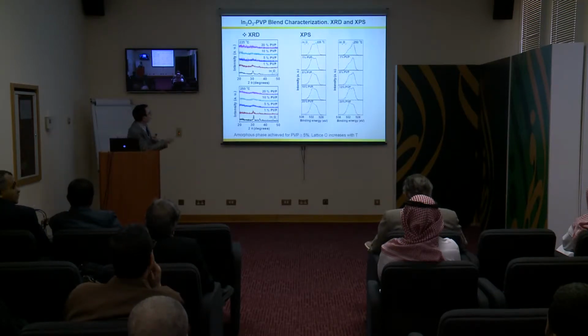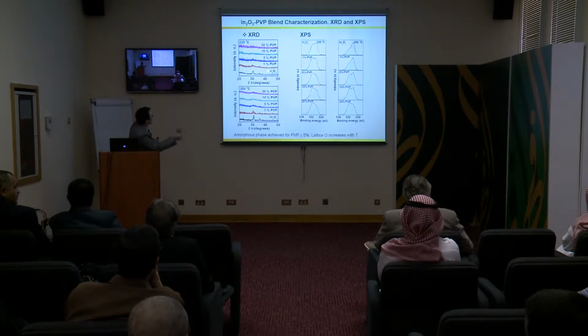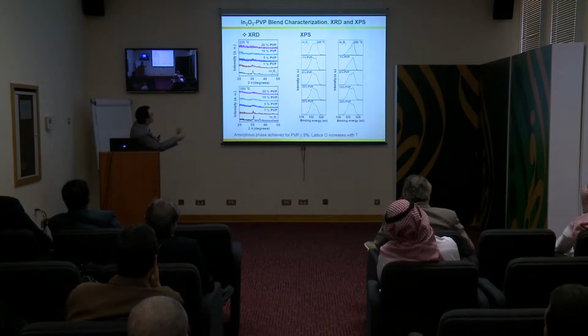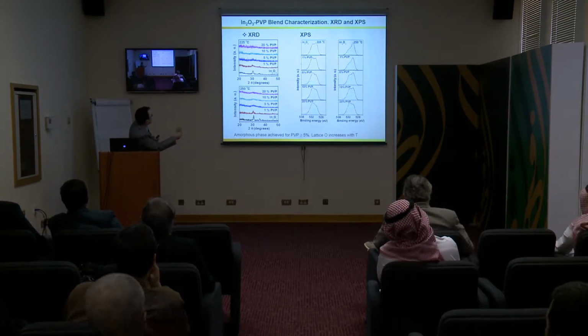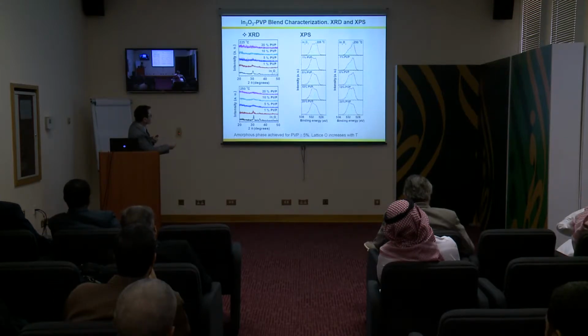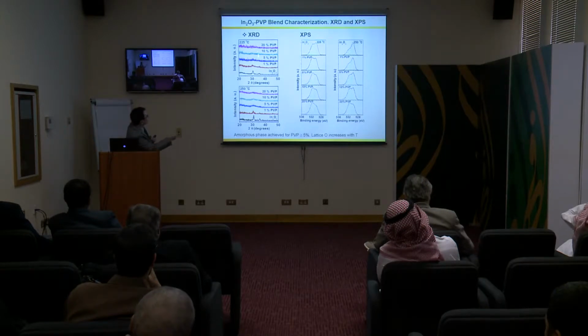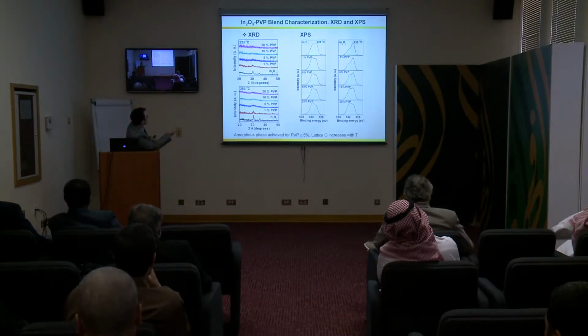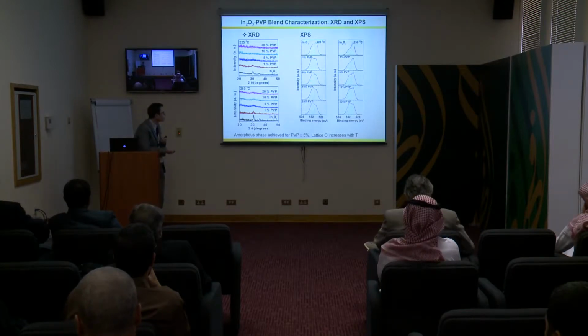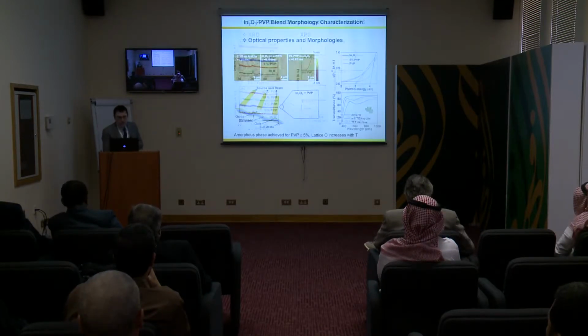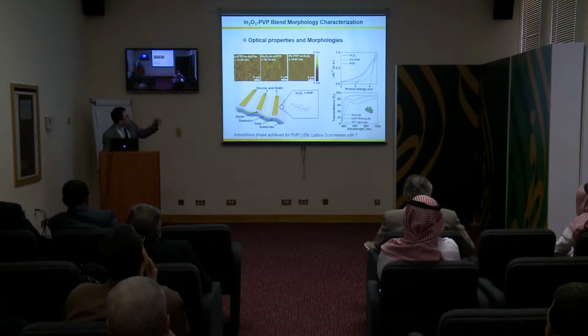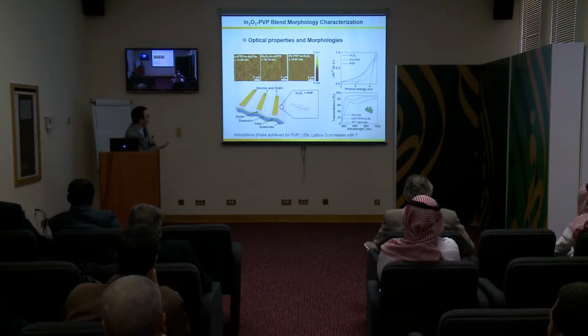The first one is these are X-ray scattering experiments. This is the matrix, indium oxide, which is polycrystalline. And then these are different doping levels in weight of PVP, polyvinylpyrrolidone. At 1% you still have a little bit of residual crystallinity, but then the phase becomes completely amorphous, okay? And this is dependent on the processing temperature. This is a little lower temperature, this is a little higher temperature. But so we can get amorphous phases. Obviously, upon addition of PVP, the film remains optically transparent.